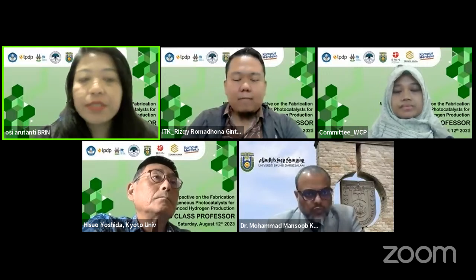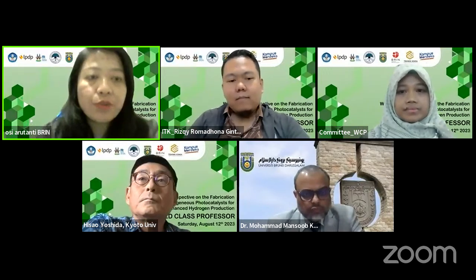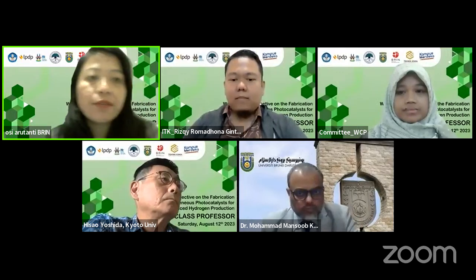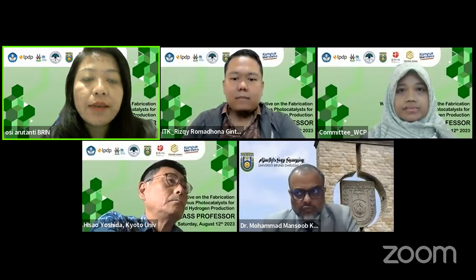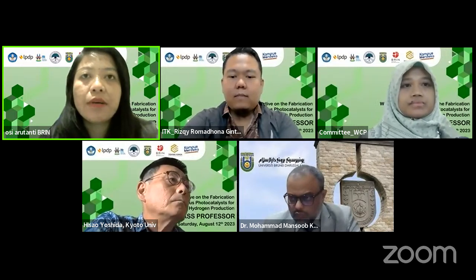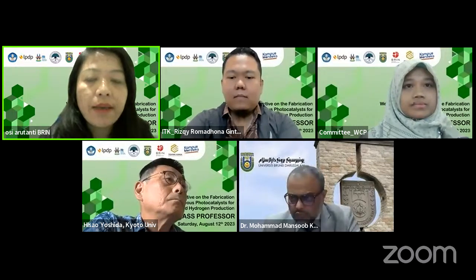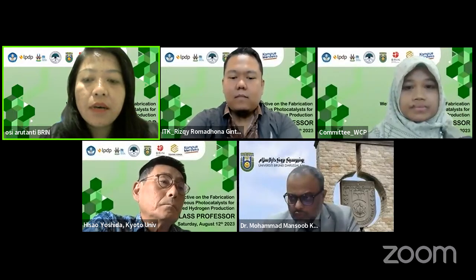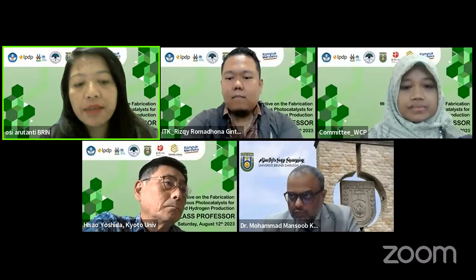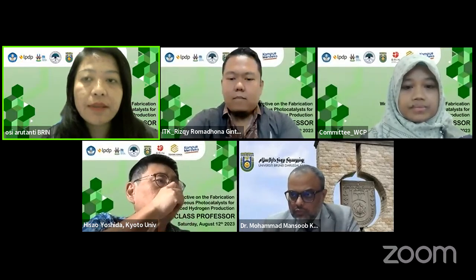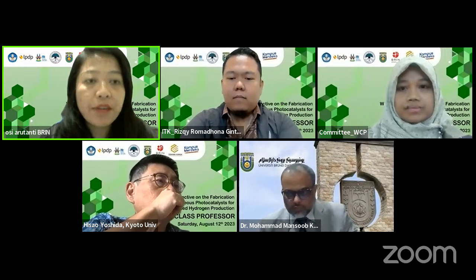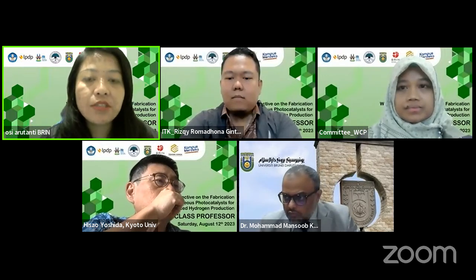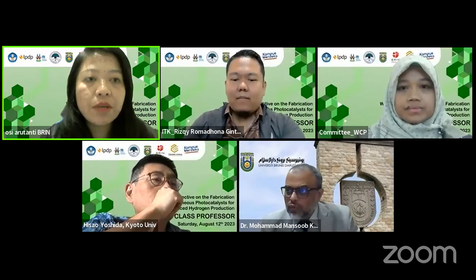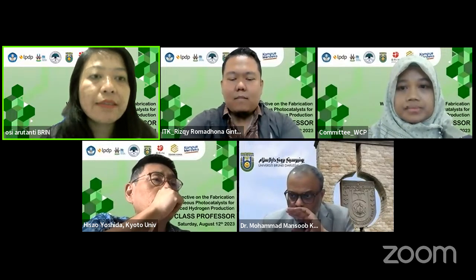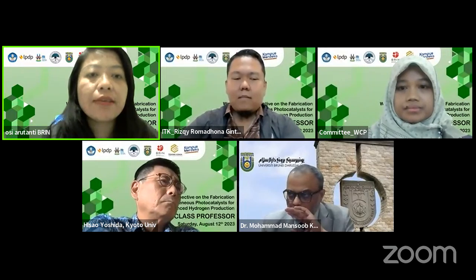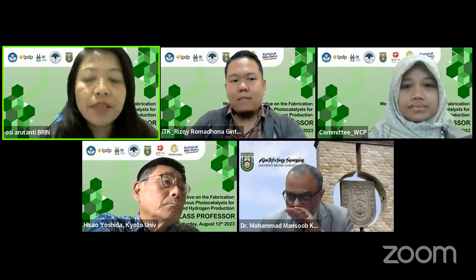Thank you very much for the questions. Yes, there are really challenges to produce the pure titanium dioxide, especially how, like the question before, to separate the titanium dioxide from Fe. And this is also tricky. After the leaching process, maybe we can get 80% titanium dioxide, and then when we try annealing the product to enhance the crystallinity, the oxidation process occurs, and the purity of titanium dioxide decreases and the Fe increases. So this is really challenging.